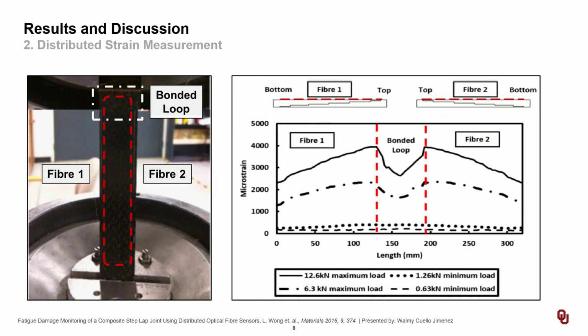Third, the top region shows greater deformation than the bottom one, which is attributed to the geometry of the specimen, with the top region having a shorter bonded thickness. And fourth, lastly, reduced strain is observed in the loop area, which is expected considering that the fiber is intended for measuring strain mainly in the axial direction.